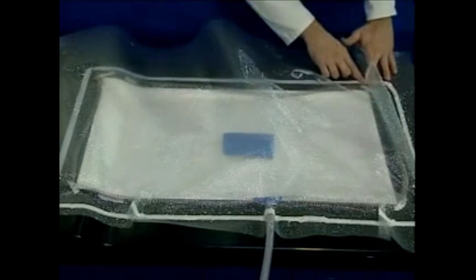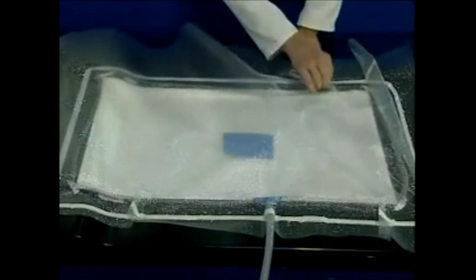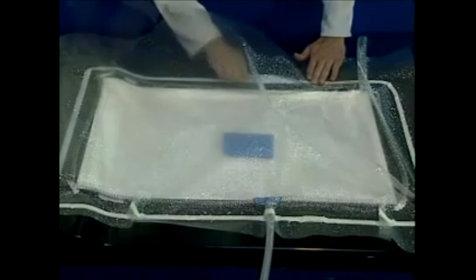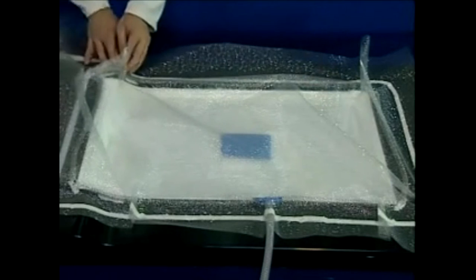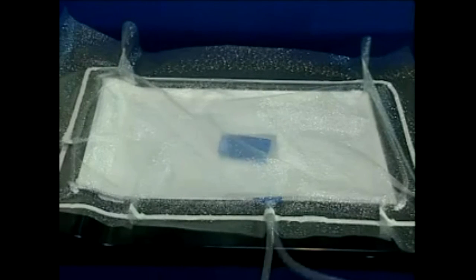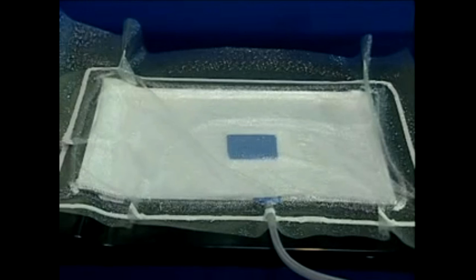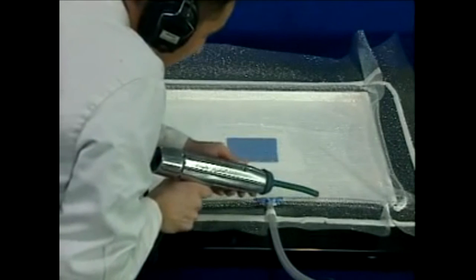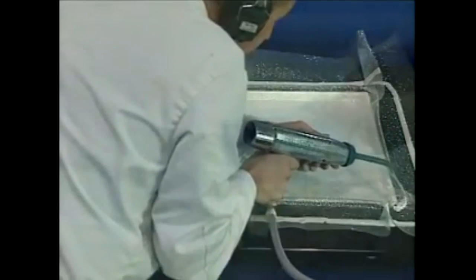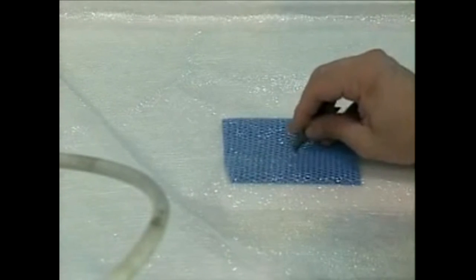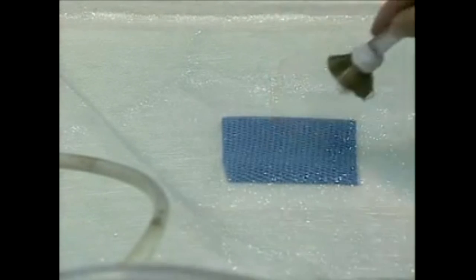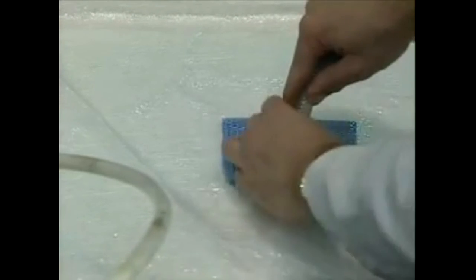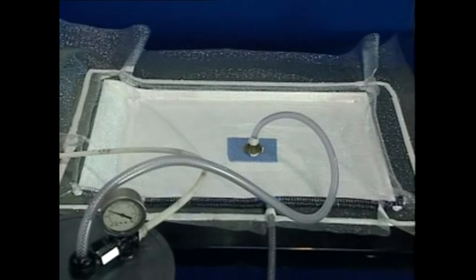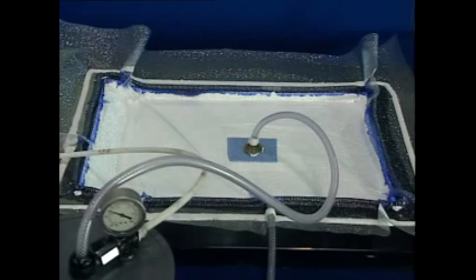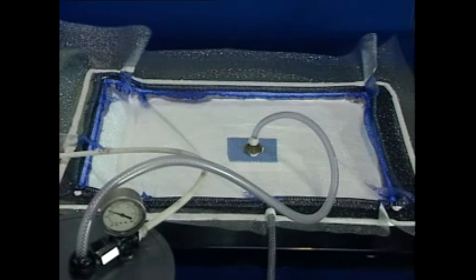The film is sealed carefully using the tape. Pleats are used to ensure that there is no bridging of the film. A vacuum is applied and the film checked for leaks. Finally, the film is slit and a tube attached in the center. Resin is fed from the outside tube into the peripheral channel with a vacuum of between 0.6 and 0.8 bar being pulled from the central point.